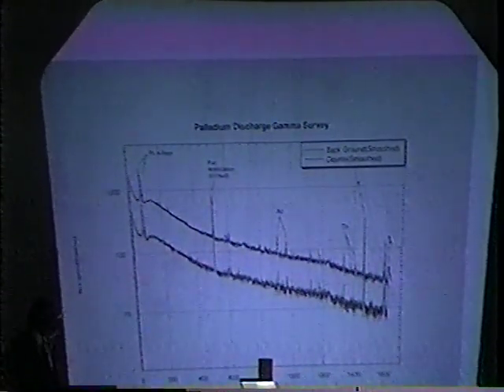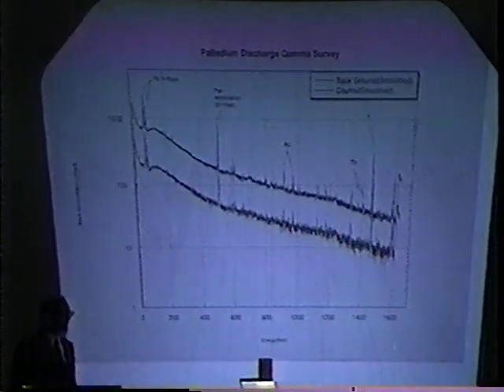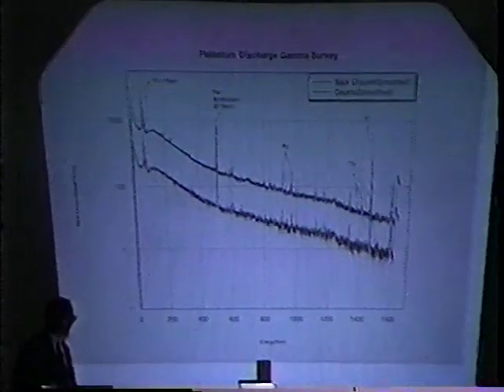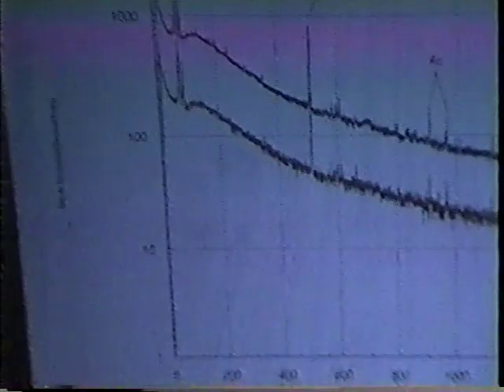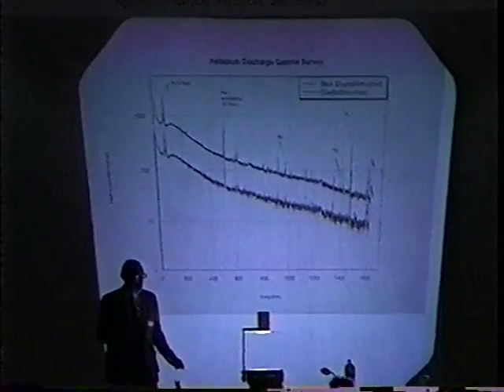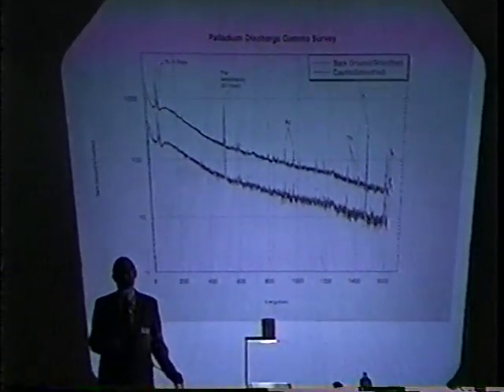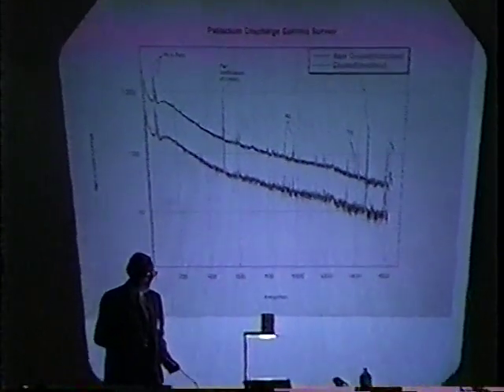All of the samples have been examined for gamma emission. This is a typical gamma spectrum showing peaks which are background. There are no delayed gammas from his samples. He has looked for neutrons under certain conditions. The amount of tritium he's making is so small that even given the known tritium to neutron ratios from 10 to the minus 5, 10 to the minus 9, given that ratio, he would not be able to see neutrons at all. So he can set a limit, but there are essentially no neutrons associated with this. And he would hope to be able to make more tritium to be able to get a more precise measure of that ratio. But there is no gamma either.